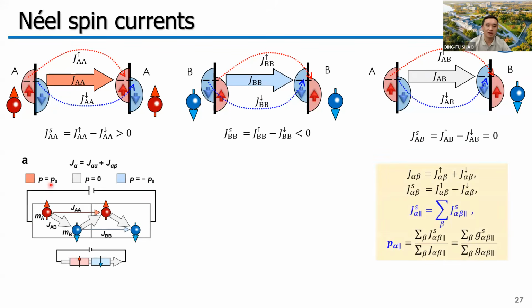So if we have such antiferromagnets where the intra-sublattice distances AA and BB are very large, and the inter-sublattice distance AB is very small, which means the hopping between AB is very strong, and the AA and BB hopping is very weak, then JAB is much stronger than JAA and JBB. We can simply consider these antiferromagnets as two antiparallel aligned ferromagnetic sublattices connected in series. In this case, the longitudinal current is mainly contributed by the spin neutral JAB.